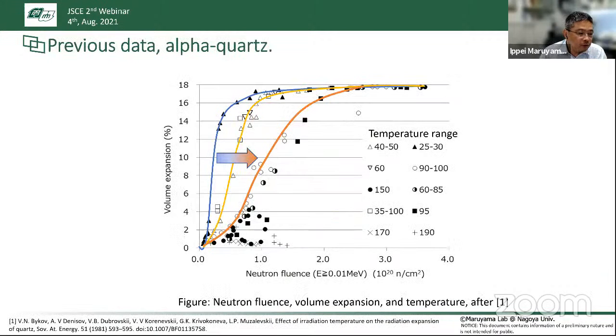And when the neutron was irradiated, the alpha quartz expanded up to 18% in volume. This is more remarkable than the results by electron irradiation. And currently, the atomic size voids, created by the bombardment of irradiated ions or neutrons, are known to contribute to this swelling behavior. Based on a review paper by Bykov's group, this swelling is affected by the temperature.